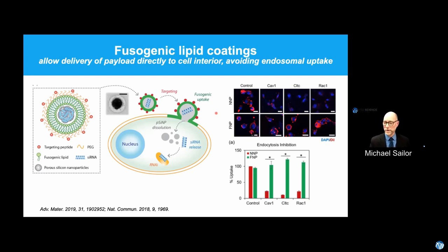And so we did a lot of blocking studies, what are called inhibitor studies, where we tried to work out: if we shut down a pathway for endocytosis, do these particles still deliver their payload into the cell? So can we tell whether they're getting in via the endocytosis pathway or via fusion? It turned out this was really important to us. And what the data shows is that when we did these inhibitor studies, we found that we are going in via a non-endocytosis pathway. It seems like these liposomes, these lipid coatings, still behave properly and they fuse to our cells. And more importantly, they're fusing to the macrophages. That was because we had the right targeting peptide on the outside, these little red dots here.